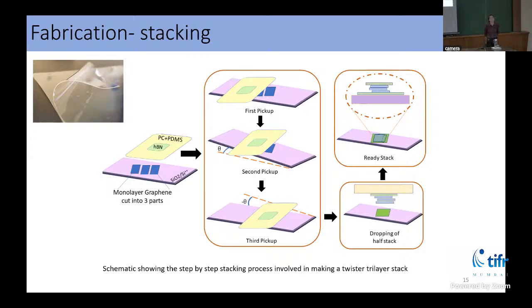Yeah, so you can understand that these are micron-level flakes, and if I try to do anything with my hand, it will be imprecise. In my previous slide, you can see that if I go from 1.5 to 1.7, I don't get as flat a band and I will not get superconductivity. So it's essential that I hit that precise angle. There are ways to get around that. Manually, we use a screw gauge to fine tune it. Now there also exist high-precision piezoelectric or motorized stages where you don't have to worry about the precision of your hand and can dial in a number and get that done.